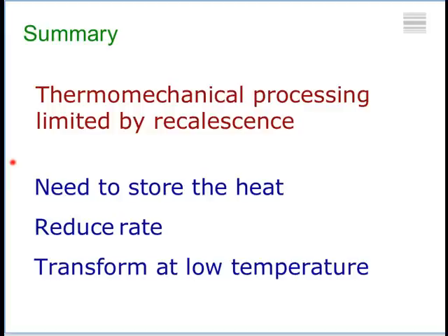Okay, now how do we do that? I'll explain to you shortly. Of course, if we reduce the rate of transformation, that also helps, because the heat has time to diffuse away. But it's clear that we need to transform at a low temperature to get a very fine grain size.